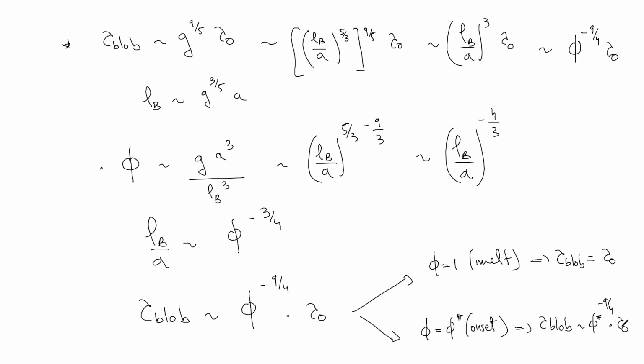And phi star is the density at the onset of semi-dilution, meaning at the moment where you can pave space with individual polymer chains. So it's n times a cube over the radius of Flory to the cube. And so it's 9/5, and here you have fifths.